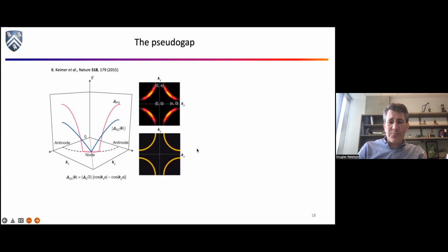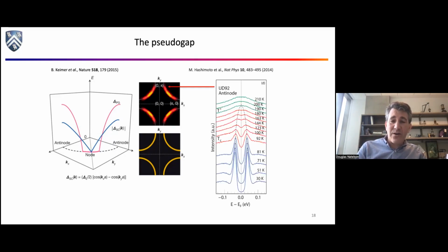So again, I know this is probably a lot of technical detail for some people, so I apologize, but I just want to point out something funky here. If you look in momentum space, at the edge of the Fermi surface, at the boundary between occupied and empty states, because of the symmetry of the material, it's got these funky arcs to it. Okay, and it turns out that in the superconducting state, the superconductivity order parameter, the thing that tells you about the pairing, because of the D wave, goes to 0 at the 45-degree points here, and here. But what's funky is it starts to have a depressed value way above the temperature before the superconductivity kicks in, right?